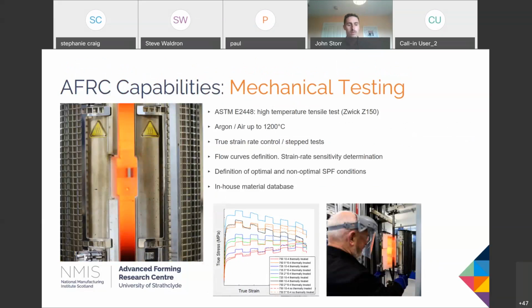Another really key complementary process we have is our mechanical testing, and Paul touched on this briefly before as well. One of the aspects of this is our Zwick Z150 machine, which is a similar setup to what I've just described in the die part interface rig that we have. You have a furnace wrapped around a die stack. The die stack is used specifically to hold a tensile component. You're heated perhaps in either argon or air, depending on the type of test, with capabilities up to 1,200 degrees. And then the test component, the tensile test, is elongated by the machine at a specific strain rate, and that allows us then to gather really crucial data about that material. And you can see an example of a strain rate jump test in the graph there.